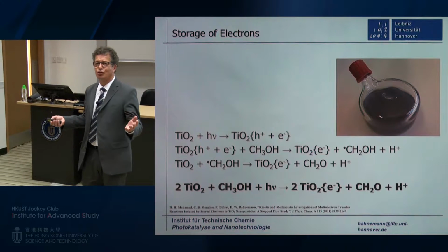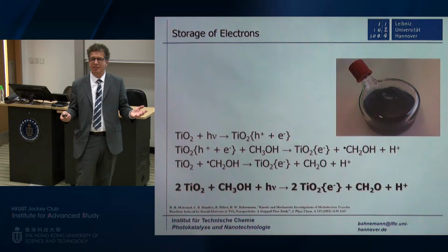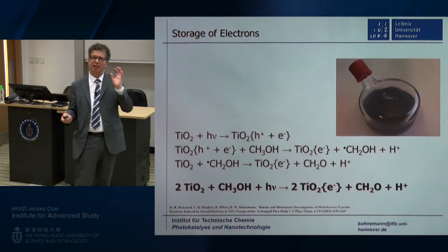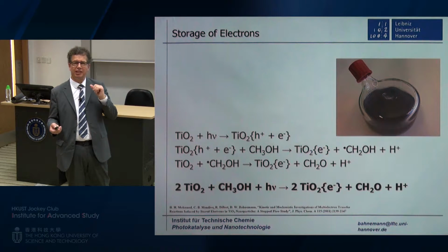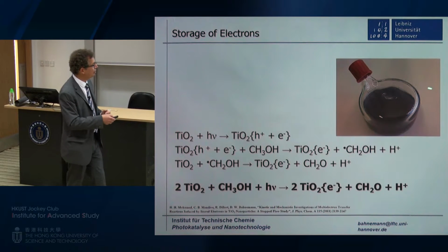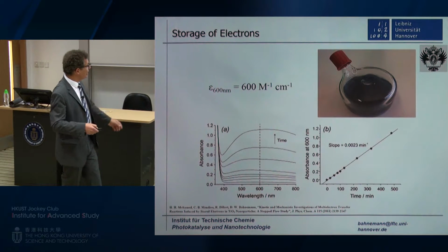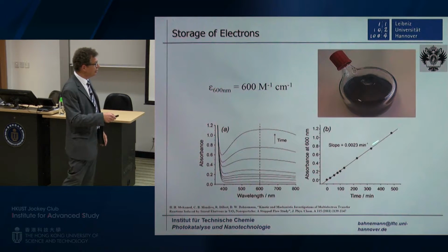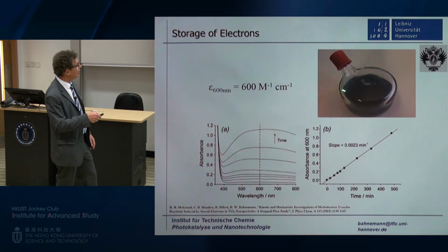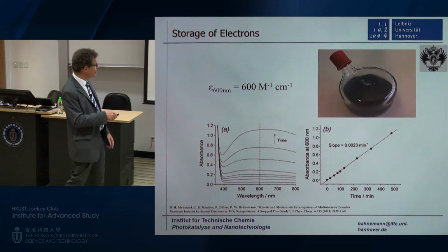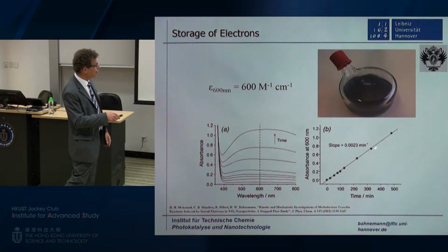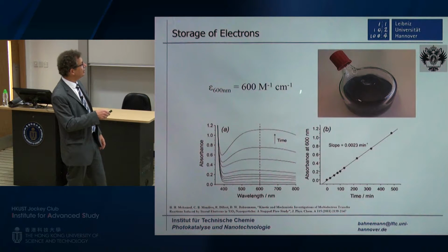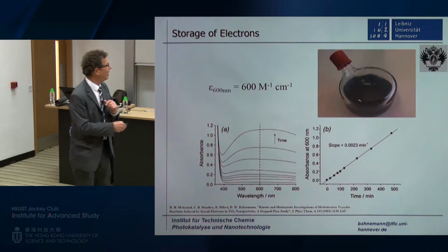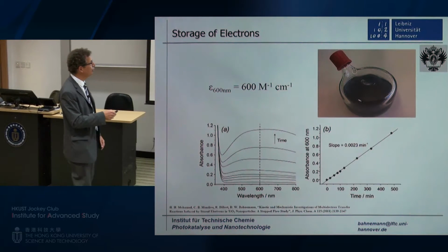This is something students in chemistry learn, I think, in their first or second year: for the analysis of titanium, it's very nice to reduce titanium from 4+ state to 3+ state, because 3+ state shows a blue color. Nothing special about this. So this is the titanium 3+, the electron in the TiO2 being located at titanium sites. And if you do this continuously, this is illumination time versus the absorbance; the maximum is around, as you can see here, 600 nanometers. You can see that this absorbance goes up and up and up and follows very linearly. Here is the 0, 0 chart, so it's very linear, following Lambert-Beer's law, and you can determine an extinction coefficient. And it's very easy to remember. At 600 nanometers, the extinction coefficient is 600 reciprocal moles and reciprocal centimeters.